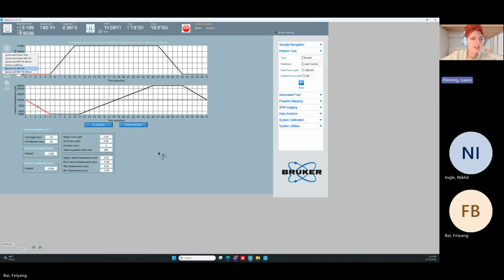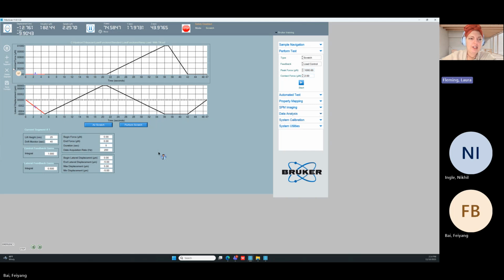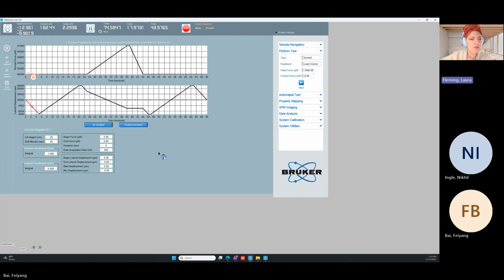And then we can add a variation on this where instead of having a constant force, we have a ramping force. Again, very similar, right? 0 micronewtons, we pull back, we trace over the scratch location. The only difference here is that we're not going to stop and load. We're loading while we're scratching at the same time. Hold, unload, comes back to 0. And you can also see it with tilt and retrace, which really looks crazy.